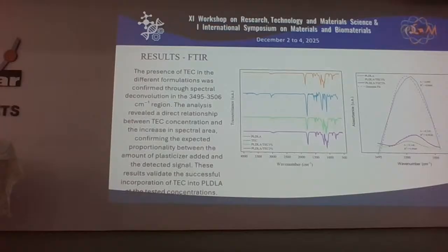Results: FTIR. The presence of the TEC in the different formulations was confirmed through spectral deconvolution in the spectral region. The analysis revealed a direct relationship between TEC concentration and the increase in spectral area, confirming the proportionality between the amount of TEC and the detected signal. This is pure TEC. This is PLDLA TEC 1% and PLDLA TEC 2%.